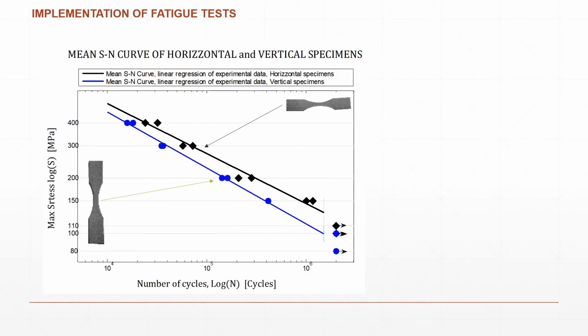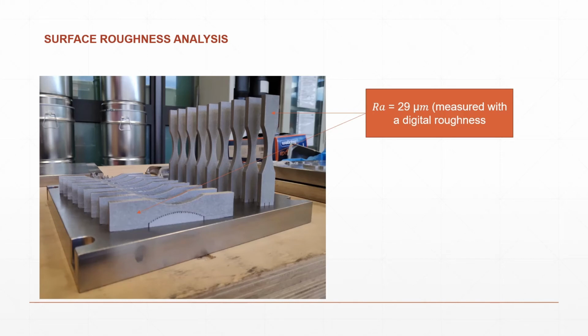Nine specimens were tested for each direction of growth, and the S-N curves were plotted by performing two run-outs for each set. As we can see from the figure, the curve of the vertical specimens is constantly kept below the curve produced by the horizontal specimens. The fatigue limit is obviously lower than the classical one that we can find in literature for the Ti-64 produced using classical technology. But let's go evaluate in detail what the causes could be.